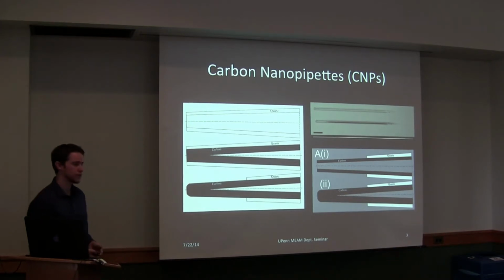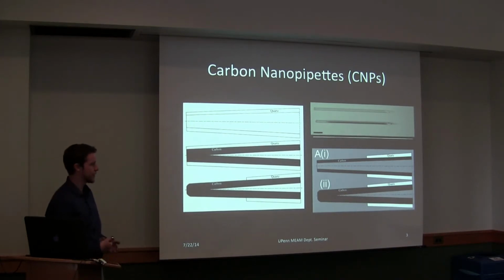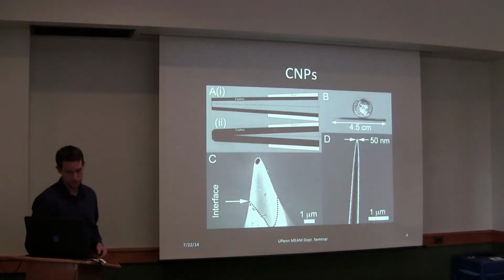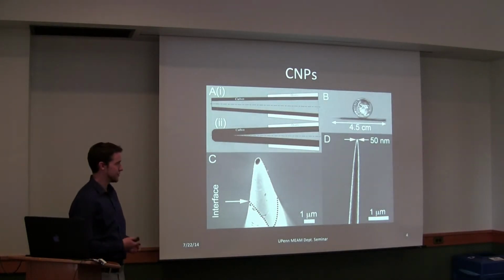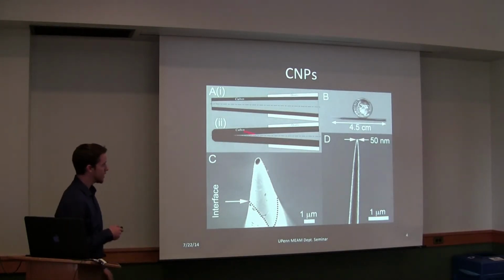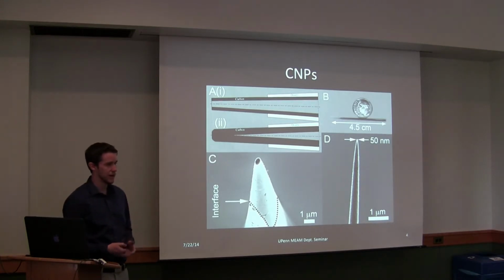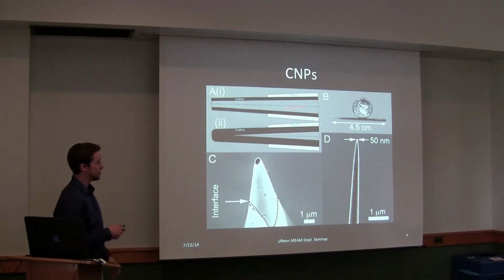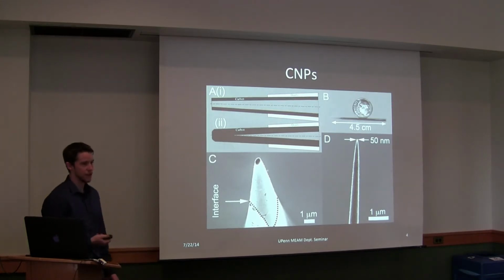And so you can control the amount of exposed carbon based on the amount of time that you etch these pipettes. Based on the deposition times, you can have either solid pipettes where you completely fill the bore with carbon near the tip, or you can leave the fluidic channel open. This is very nice since we now have a continuous fluidic pathway from the macro scale to the nanoscale, so you can still do microinjection and things of that nature.